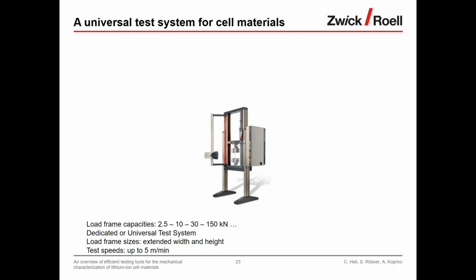Okay, so to sum up, all these tests actually can be used with our testing machine. Here we offer load frame capacities from 2.5 up to 150 kilonewton or even higher, depending on the standards that you want to follow. We offer dedicated systems which perform one single test, or we offer universal test systems which can be combined with different types of tests. We offer different load frame sizes. Depending on the specimen size, can be either extra wide or extra high load frames, and we offer the required testing speeds for the abuse tests, which can go up to 5 meters per minute.